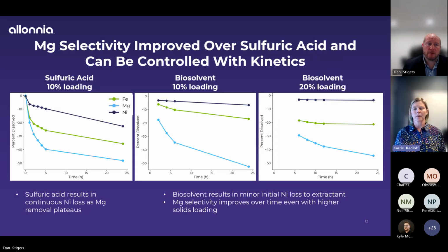Next. So the one thing that we saw with this, and we got that indication with the temperature graph, is that the magnesium selectivity can really be improved over sulfuric acid with the kinetics. If we look at the sulfuric acid extraction on the left, this is showing the percent dissolved, the same figures as before, but showing how that reaction progresses over time. We see that the sulfuric acid is readily dissolving things, and that reaction continues. So with increasing time, you're just getting more nickel loss.